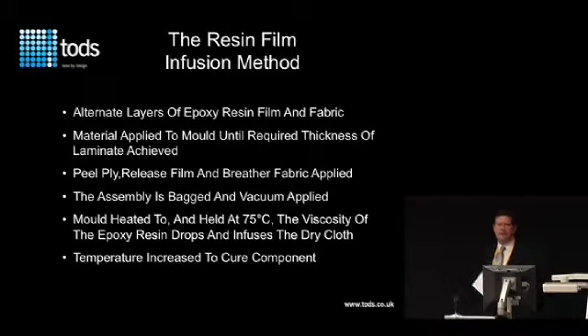The second method that we considered was the resin film infusion method, where you've got alternate layers of epoxy resin between fabric. You apply the material to the mould until the thickness is achieved. Again, you bag it using the traditional materials of release film, breather fabric, vacuum bag. You assemble and then apply a vacuum. You then heat the mould, and obviously its contents, to approximately 75. At that temperature, the viscosity of the material drops, and under the influence of the vacuum, infuses your product. You then increase the temperature to cure the resin.